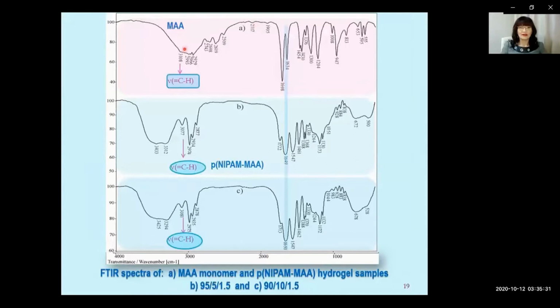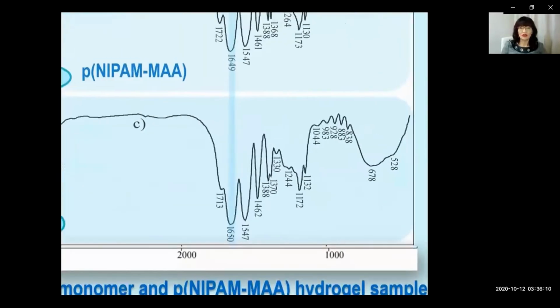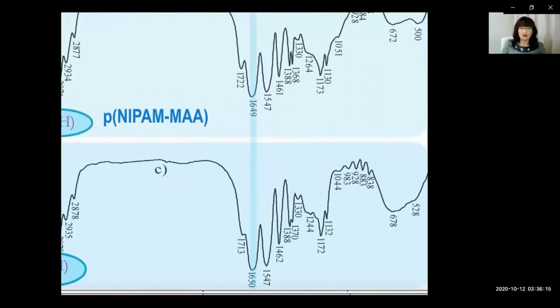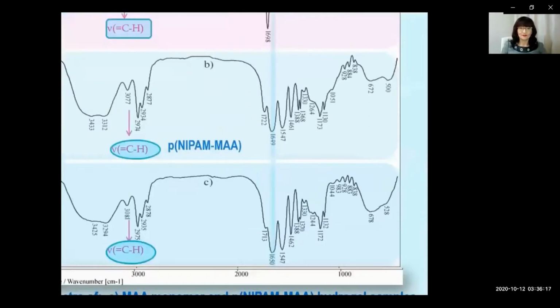FTIR spectrum of methacrylic acid is on the top, and FTIR spectra of poly-N-isopropyl acrylamide co-methacrylic acid with 5 and 10 molar % of methacrylic acid co-monomer have structures different from the reactants, with new bands which are absent in the spectra of reactants, and absence of absorption bands from valence vibrations of carbon-carbon double bond, confirm successful polymerization process.